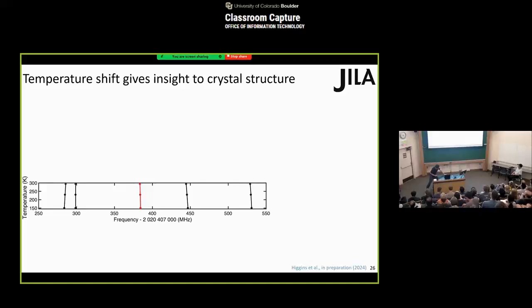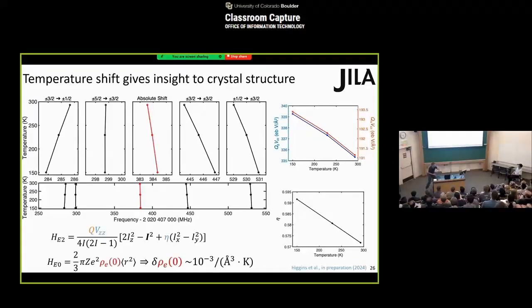Essentially, the shift, we think, mostly comes just from thermal expansion, and it roughly makes sense. The thermal expansion coefficient is on the order of 10 to the -6 per Kelvin. And if you look at this monopole shift and quadrupole splittings, their total energy scale is on the order of gigahertz. So essentially, if you have a 10 to the -6 shift of about 1 gigahertz total interaction energy, that comes down to about 1 kilohertz per degree, which is about what we observe in these line shifts. So we think it aligns pretty well with just thermal expansion of the crystals.